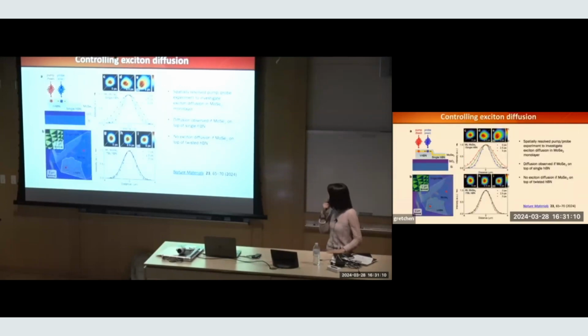Okay, so now we again start with the simplest thing that we're most familiar with. We put a semiconductor on top, have a monolayer semiconductor, partially overlapping with a single hBN, partially overlapping with a twisted hBN. On a single hBN, I can see the diffusion of the exciton. On twisted hBN, I no longer can see the diffusion. So that shows you the potential is localizing the excitons, at least to the resolution I can measure. Okay, it's doing something to the exciton.